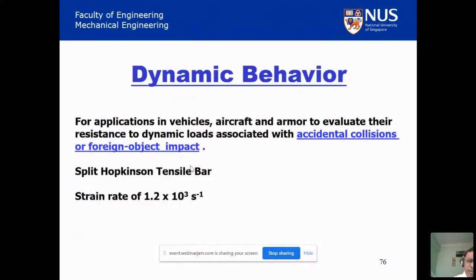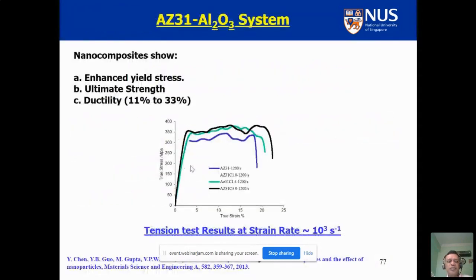Dynamic behavior is very important for people in the transportation industry, because in case of an accident, your loading is not slow. The loading imposed during collision is high strain rate loading. So I worked with my colleague who is an expert in that and in the use of the split Hopkinson bar. And we realized for AZ31, which is a commercial magnesium alloy, with Al2O3, you see this graph and focus on the blue curve here, which is the unreinforced material, and the black curve, which is the nanocomposite material. So you can see an increase in the strength and ductility in the case of nanocomposite material.